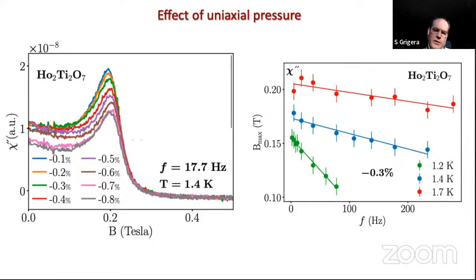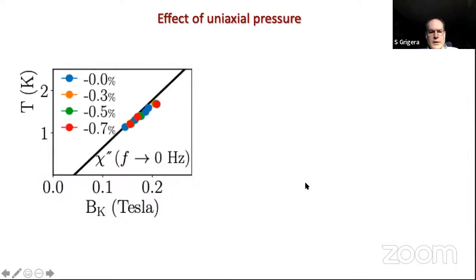Higher than that, the samples break. And now you see that, if you want to compare this, we cannot do any DC measurements here. So essentially what you do is you measure at different frequencies, you extrapolate that to 0, and now you compare that. You create a phase diagram for the different tensions, and essentially you see that there's almost no difference between them.